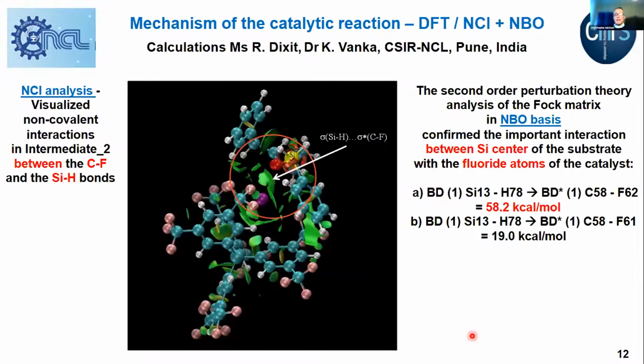So looking at it by DFT calculations with NCI analysis and NBO analysis, Ms. Rishi Dixit and Kumar Vanka at Pune could evidence, in fact, such non-covalent interactions between the carbon-fluoride and silicon-hydride bonds. You can see here interactions between the sigma orbital of the Si-H bond and the sigma star orbital of the carbon-fluoride bond. And this was further confirmed by NBO analysis. We obtained favorable energies for such interactions of 58.2 kilocalories per mole.